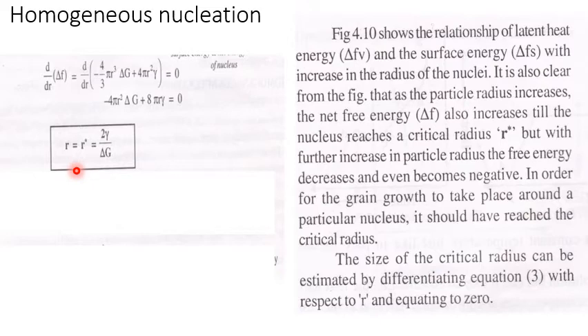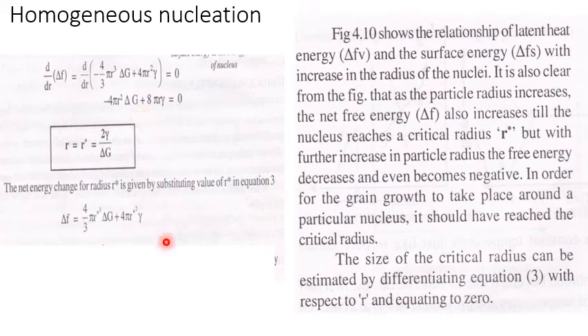Now what is the critical free energy which we are going to get? By substituting this r star in equation number 3, we get delta F equal to 16 pi gamma cube divided by 3 delta G square. This is known as the activation energy. In order to form this critical radius, that is, to start the nucleation in a pure metal, the energy which we need to supply is the activation energy, given by 16 pi gamma cube divided by 3 delta G square.